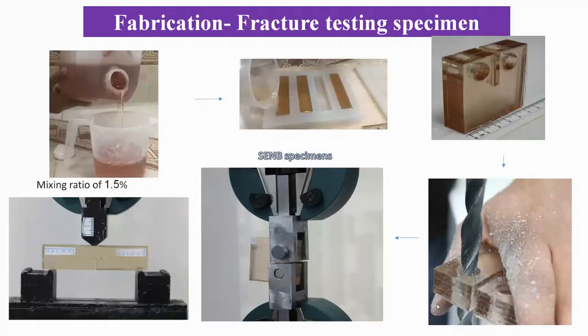The next step is preparing specimens for the SENB and CT tests. Resin and hardener are mixed, similar to the tensile testing specimens. The specimens are poured and cured in silicone molds, and the silicone molds were made with the help of wooden and acrylic models. The holes were finished by drilling, and the last pictures show the SENB and CT specimens under fracture testing.